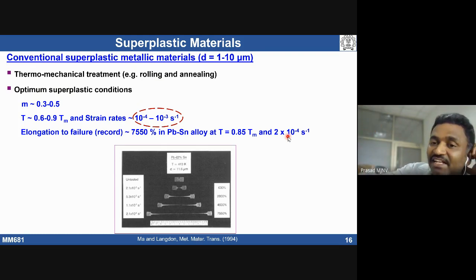But at high strain rates, your m value is going to be low. Cavitation can take place very easily. The dominant mechanism is going to be the dislocation creep mechanism, as compared to grain boundary sliding. So such a low strain rate is one of the drawbacks of superplasticity. We need to have relatively high temperatures and low strain rates.